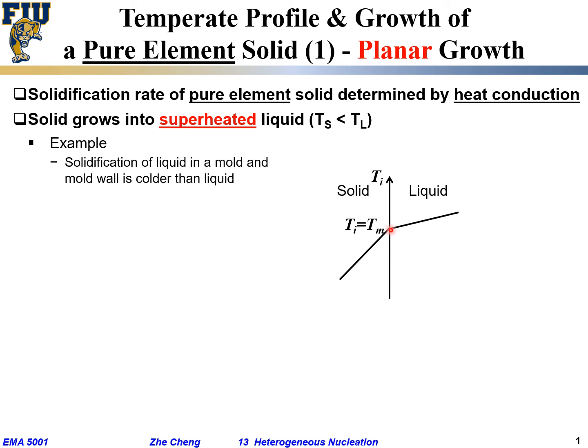And at the interface between solid and liquid, solid here we mean the first bit of solid crystal that formed versus the liquid, at the interface, the temperature is equilibrium melting temperature, or TM. Okay, under such situation, we mentioned the solidification rate, or essentially the growth rate of existing solid, is primarily determined by heat conduction, or how fast one can extract heat away from the system, in this case into the deeper solid. Okay, and to get an idea of the rate, we need to consider the balance of heat flow.